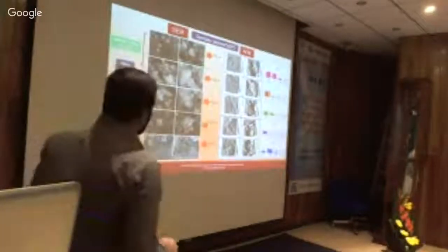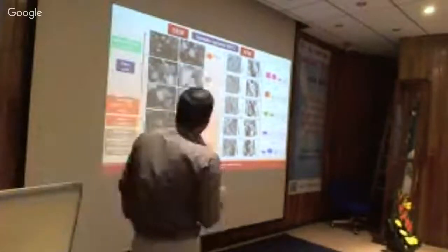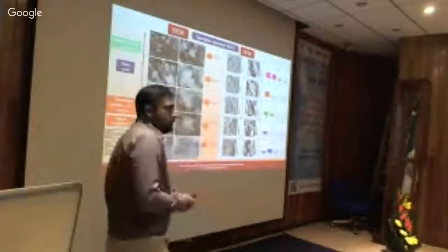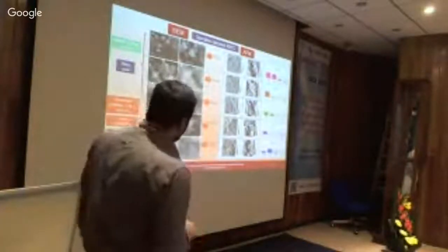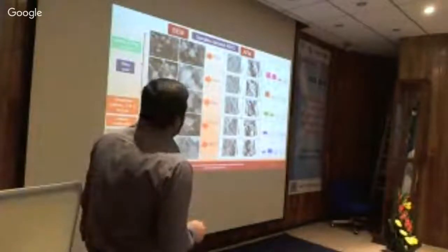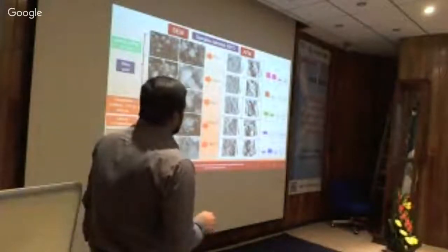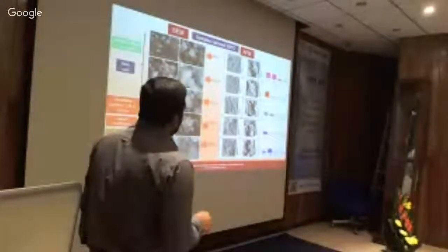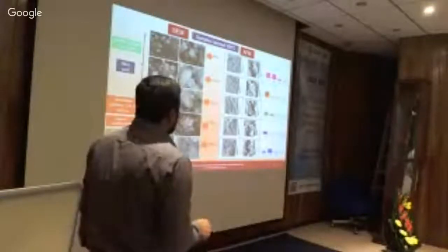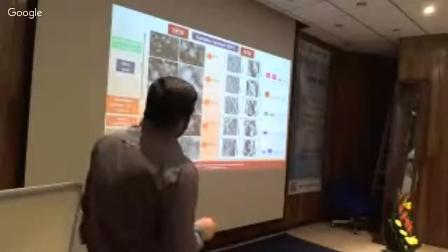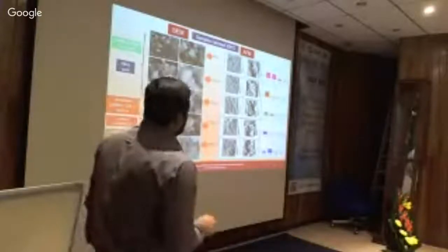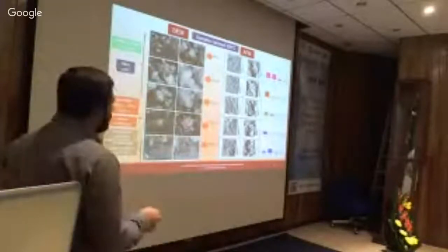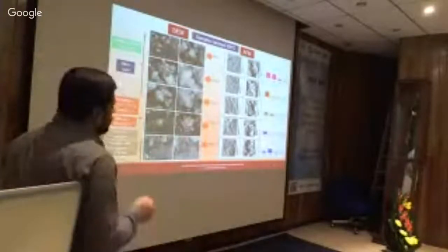So in order to observe more clearly, we did the AFM analysis, where we can see that an increase in the pH tries to form microstructures, like rod-like structures of hydroxyapatite, and these values denote the particle size. Here you can see pH 8 and pH 9.6 have similar particle sizes, from 15 to 18 nanometers. The particle size is smaller, and there is another range which is really big, and we can see for pH 8 there is a more homogeneous distribution compared to the others.